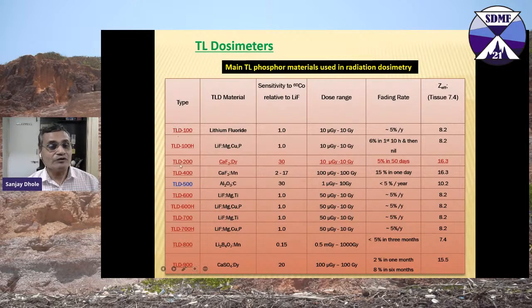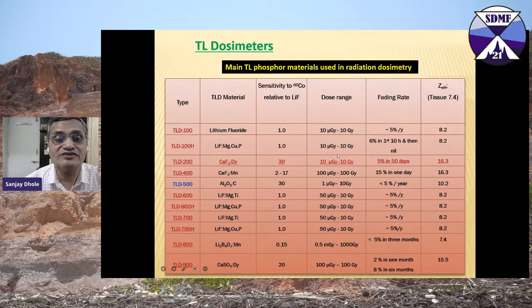Okay. There are all the types, because their nomenclature has already been defined: TLD-100, TLD-100H. TLD-100 is lithium fluoride, and its sensitivity to cobalt-60 relative to LiF is 1. So these are all the standard dosimeters which are available nowadays, and which are already commercially available. But if you look at their dose ranges, for example, TLD-100, that is lithium fluoride, which is a very popular one, can go from 10 microgray to 10 gray. But really, if you think it can be used in medical application, where you need to have dose measurement less than 1 gray, this is good enough.